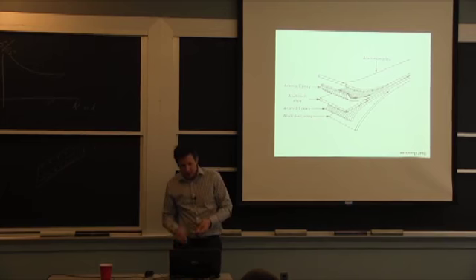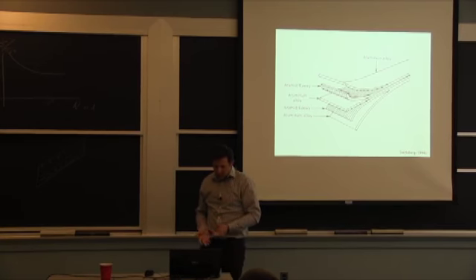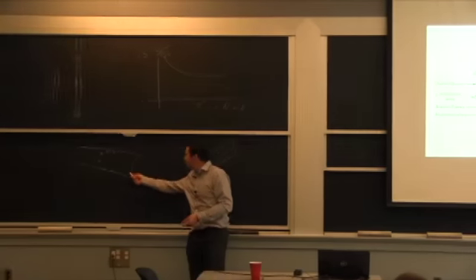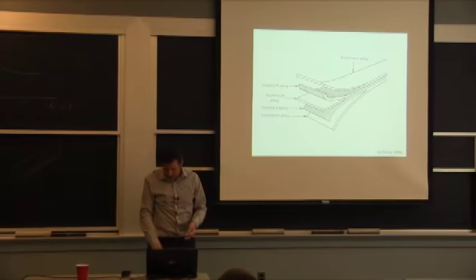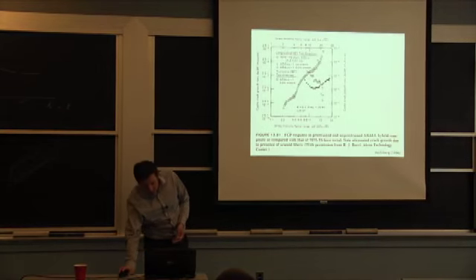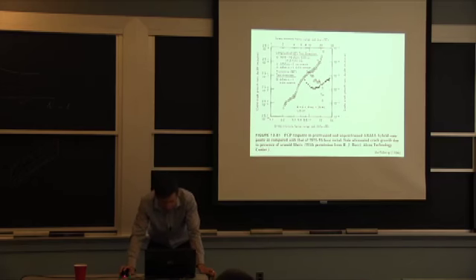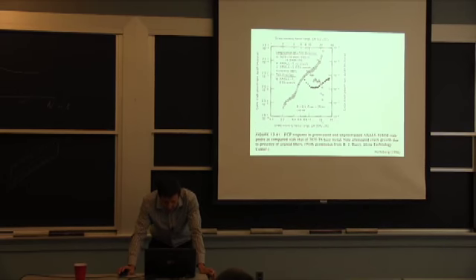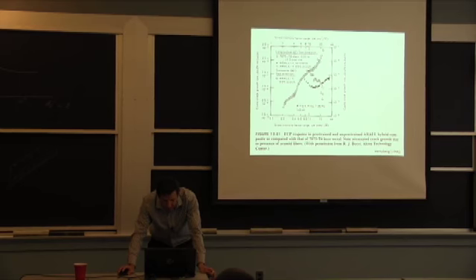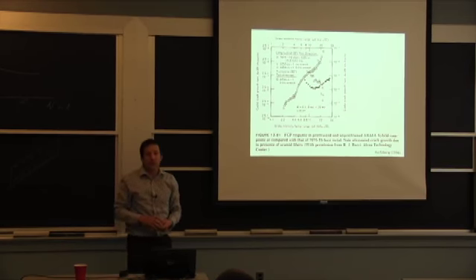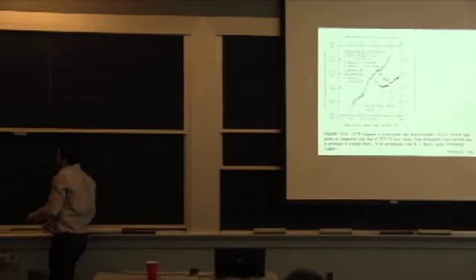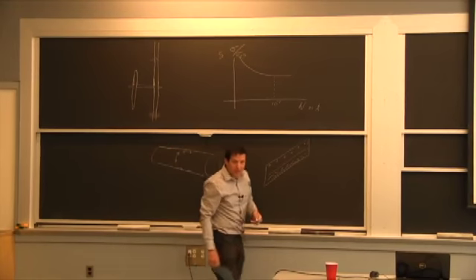This is one case of a sandwich structure that puts together aluminum and an epoxy glass reinforced composite. So the intention was for fuselage applications. And one aspect you can see is how you can reduce the crack propagation rate. So these plots, we haven't dealt with them too much, but you're looking at a logarithmic crack growth rate here. So there's a factor of 10 in rate between each line, and then we're looking at a stress intensity. So how much load is on our sample. So if you get to relatively high load, let's say we take 20 here, we have about two decades difference, so 100 times difference in rate between having or not having these fibers to bridge an existing crack.